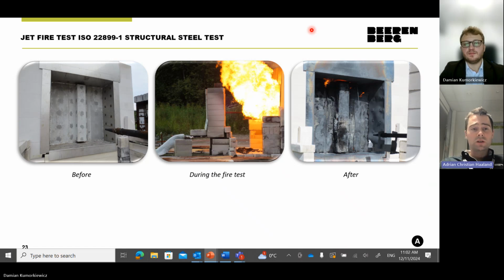Quick snapshot from a jet fire test. This was a structure one-sided panel application. You will see the panel fixed on the left picture here. A one-sided application with an I-beam on the wall in the center here, which is why you see this box coming around the center beam. Subjected to 2 hours of high heat flux jet fire testing, and on the picture on the right you can see a typical post-test picture of how it looks. The Chartek will be various degrees of eroded. The stainless steel core will typically be retained, and the object will remain hot for some period of time after the test is shut off.